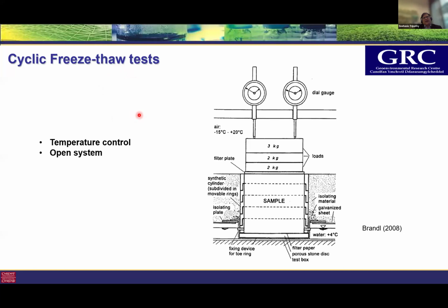The important points to note in this kind of test are that the test may be performed in an open system. That means the soil should have access to water during the freezing cycles. The other point is that when we lower the temperature, at one end of the sample, water turns into ice and frictional resistance gets developed. It is not easy to get rid of the frictional resistance, which is also known as the adfreezing effect. As you can see in the figure, the researcher has used movable rings in place of a single cylinder in which we have the soil sample. When the freezing front moves downwards, the sample freezes at the top and expands in a downward direction, and the ring gets lifted in an upward direction. So it is quite a complex testing process when you are trying to do a cyclic freeze-thaw test.